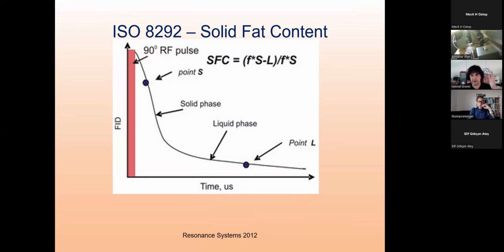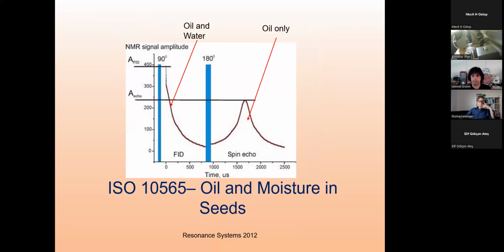You put the sample inside the NMR, and you observe a simple experiment. You give one pulse and observe the free induction decay. And what is decaying fast, like you saw in the starch? Here, for fats, the fast decay is characteristic of the solid fat, and the long decay is characteristic of the liquid fat. And you don't need to do any chemical exercises. You just put the sample and measure the solid fat content, as a ratio between the amplitudes. For example, this is S, what we measure in a short time. This is what we measure in the long component. To estimate the contribution of the solid fat, we need to subtract the 2 amplitudes and then divide by this S value. So this is one of the simplest applications, which appeared, I guess, 30, maybe 40 years ago, maybe even more.